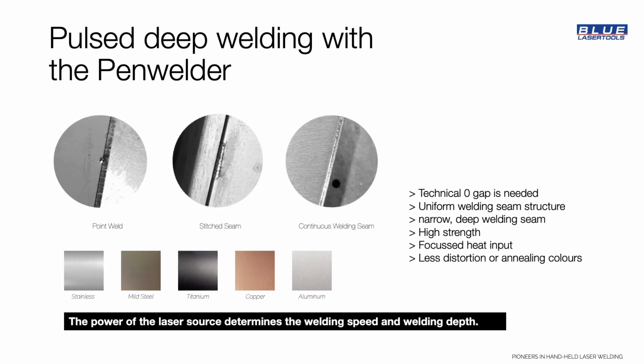The Penwelder is exclusively operated in the pulsed deep welding process. Work is carried out without filler material, which is why a technical zero gap is required. This means that the joining gap must not exceed 10% of the material thickness or must not be greater than 0.2 mm. During deep welding, the laser beam not only melts the metal, but also forms a deep, narrow steam-filled hole, the so-called steam capillary or keyhole.